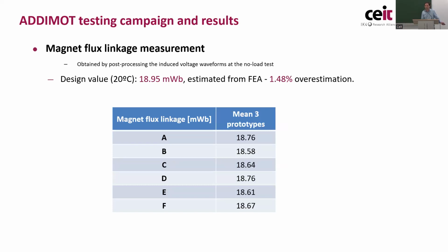Then more importantly, the magnet flux linkage measurement. The magnet flux linkage is key for the behavior of the motor, and the predicted value was 18.95 milliweber. The measured values were very close to it, practically the same, a 1.5% overestimation of the magnetic flux linkage. So with this measurement, we were more relaxed because the machine was quite okay.